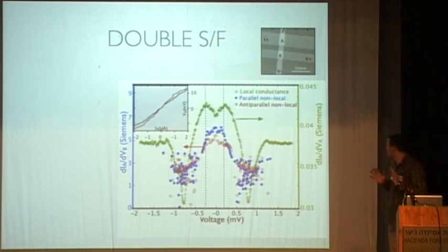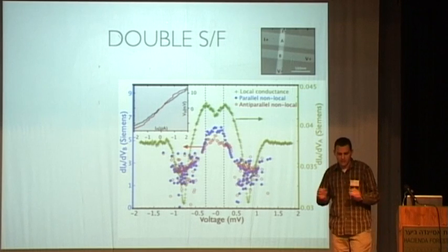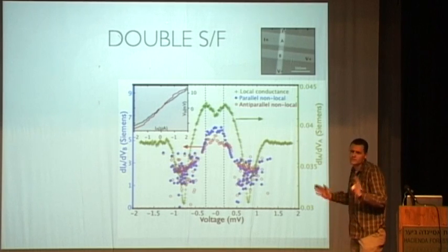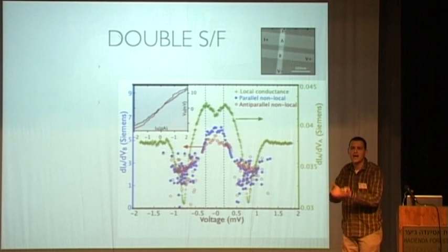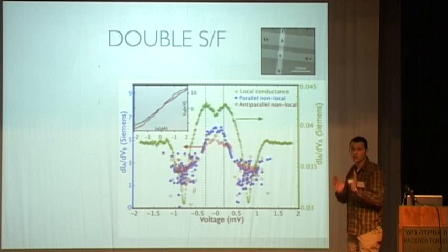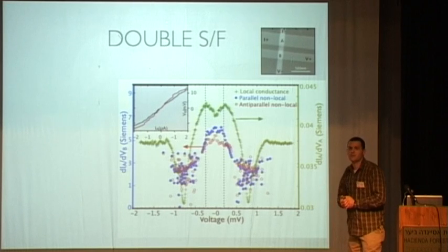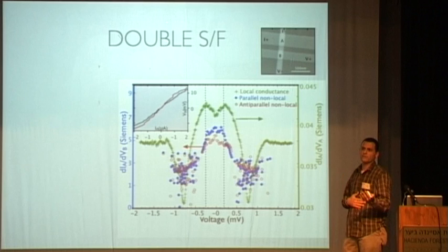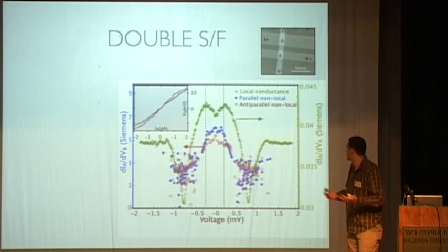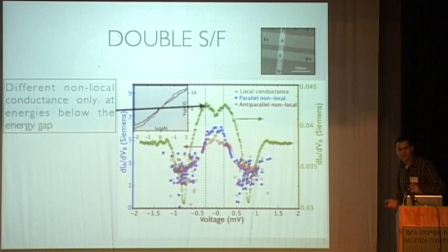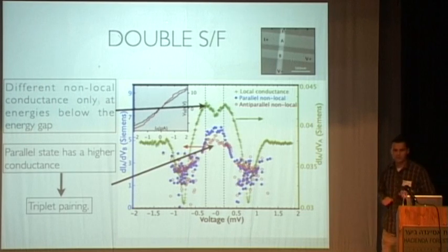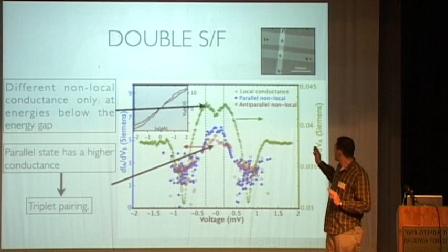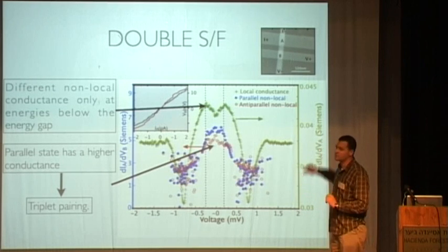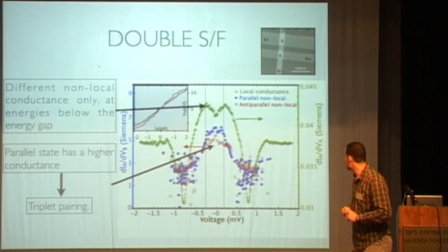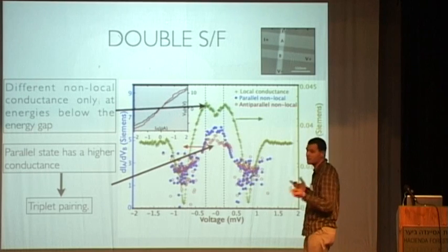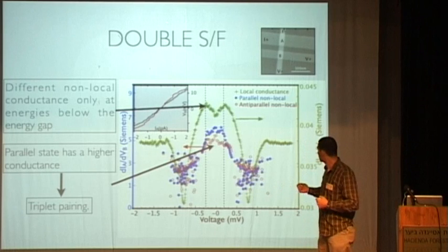And I'm showing here three graphs. The green one is the regular local conductance of junction A, which is just, as I showed you before, it has a cusp, is anisotropic, it's reassuring. And the two other graphs, the blue and the red one, are the parallel configuration and the anti-parallel configuration, and we want to see which is bigger. And basically what we see is two things. The first is we see that all interesting stuff begins at the conductance peak. The peaks of the green graph is the beginning of all the interesting stuff. I mean, at energies below this conductance peak,